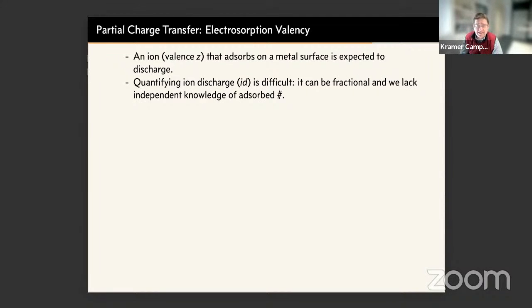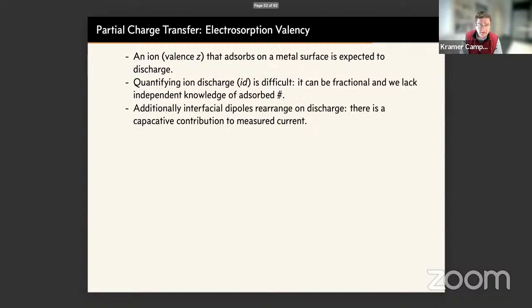The problem is that it can be, of course, fractional, right? And we lack independent knowledge of the adsorbed number and the extent of discharge of the adsorbed ion. Additionally, of course, there's the problem that when an ion discharges, the interfacial dipole changes, and one might expect local solvent structure to change and the total dipole of the interface to change as a consequence of this ion discharge.